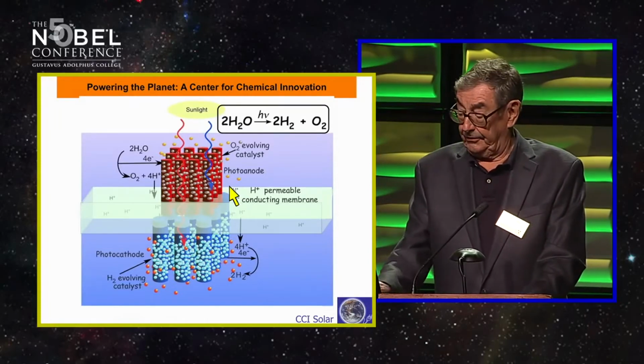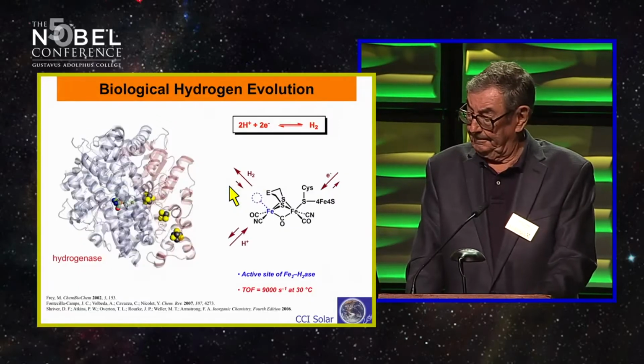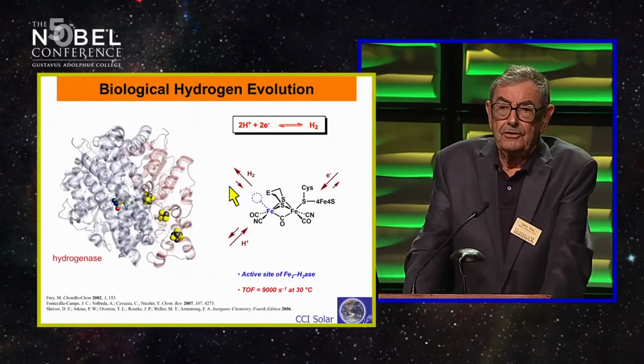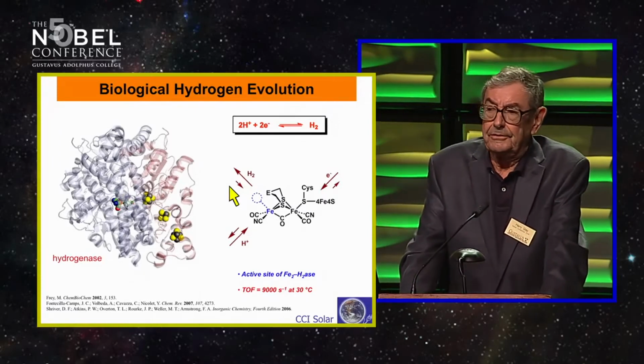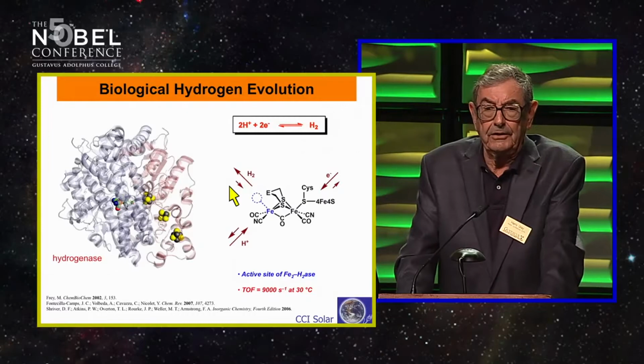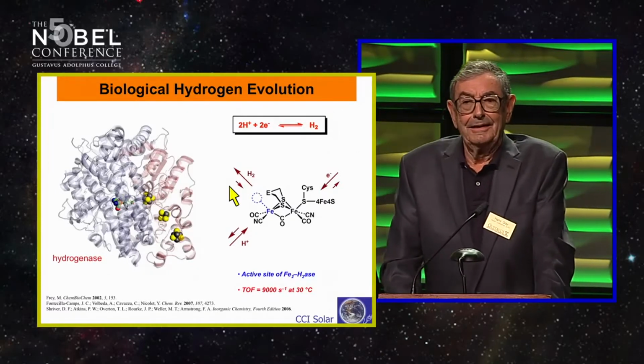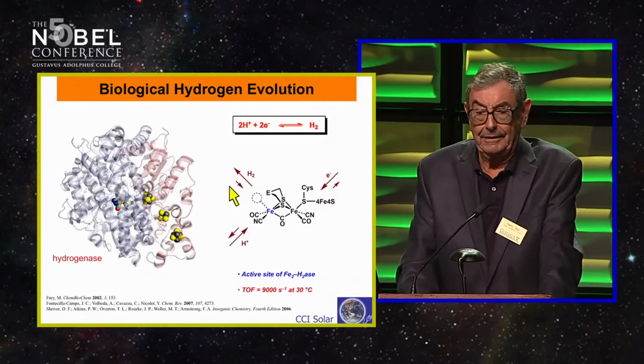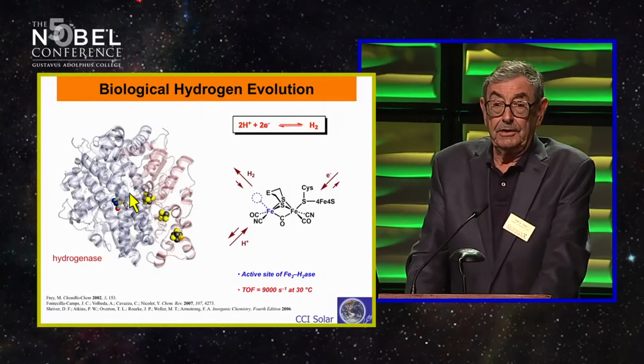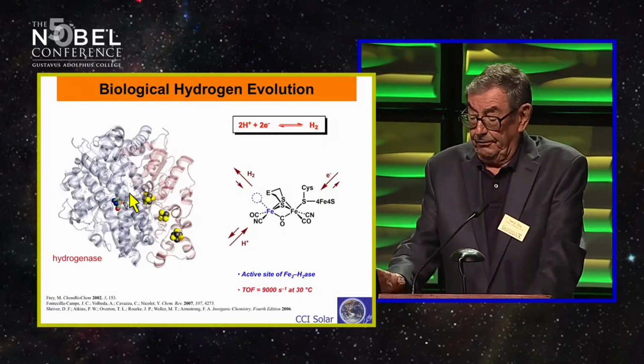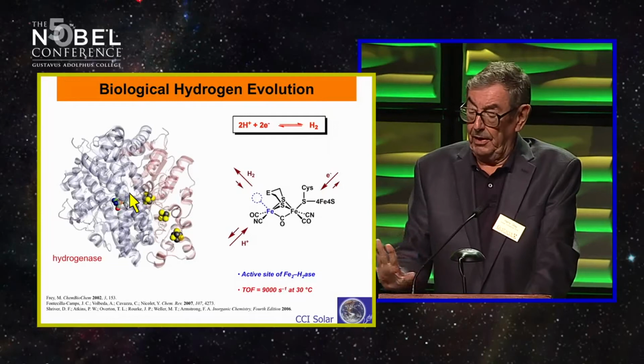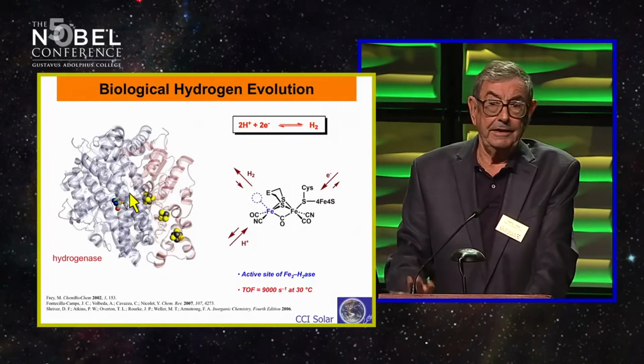First, the catalyst to replace platinum at the cathode. When you think about cheap, earth-abundant materials, as Brandy would point out, you think about what nature did, because nature couldn't afford to use platinum. Nature had to use iron to evolve hydrogen. There are enzymes called hydrogenases that are very, very active at catalyzing the reduction of water to hydrogen. But if we put these protein molecules on our silicon photocathodes and start irradiating, they're very fragile, and they irradiate away in a few minutes. So we can't use them.